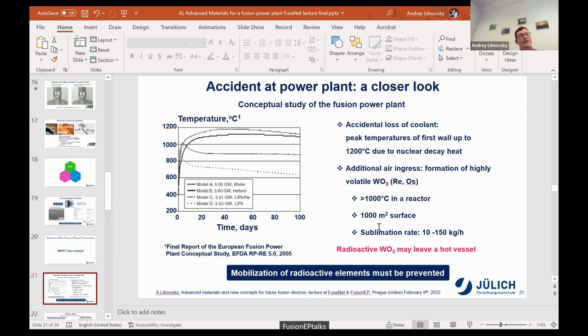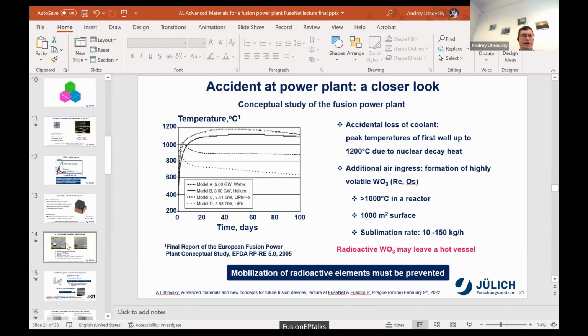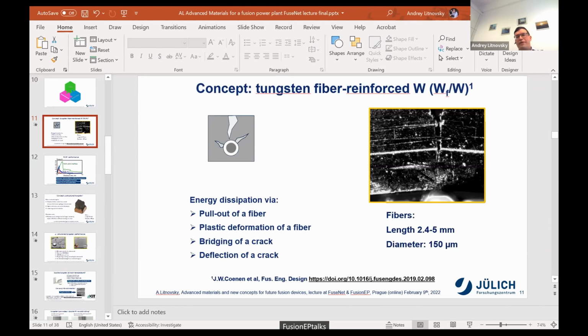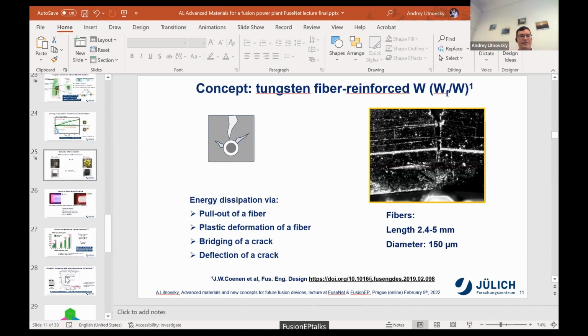The second question is on tungsten-fiber-reinforced techniques. There are several, and they are still competitive techniques of producing this. I'm very impressed by how these guys did these things. First is FAST, where you simply put all these fibers in the matrix and sinter. Initially, one needs to deposit an interface layer as a barrier, because it has to be a weak interface between the matrix and the wire, for instance in a magnetron device. So all these wires are first coated, then put into the FAST device and sintered as a whole.